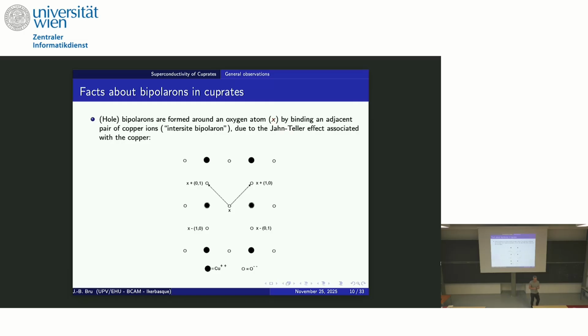So, for example, some group of experimental physicists like Müller claim that there is evidence, not only for them, it's clear that there is a formation of bipolarons in that kind of system with spin 0. So the idea behind this exchange interaction is the following. You have a pair. The pair is moving on the lattice. It is shown experimentally that it is moving within the oxygen, not within the copper. And sometimes it gets trapped and forms a bipolaron, and sometimes it is released.